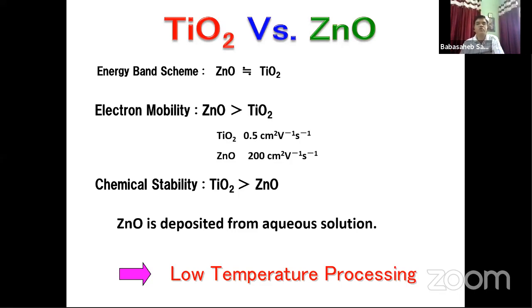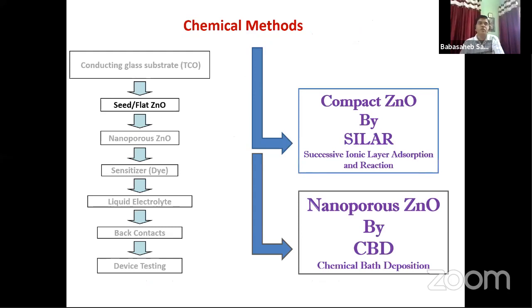So how have we deposited this zinc oxide? We have used a simple chemical method, that is chemical bath deposition, where cationic and anionic precursors are placed together. Another method we have used is SILAR, which is a modified method of chemical bath deposition, called successive ionic layer adsorption and reaction, where you can place cation and anion separately instead of putting them together.